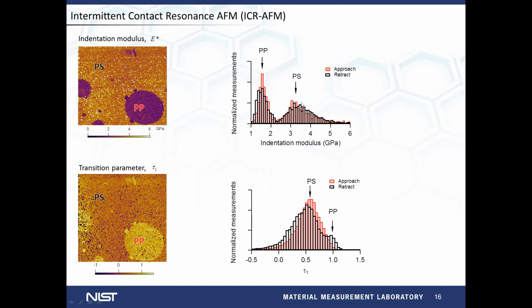Polystyrene was used as a reference material with the elastic modulus 3.4 gigapascal. Polypropylene was 1.5 gigapascal. But interestingly, there was also contrast in the transition parameter map. As we see the difference between these two materials, the value for the polypropylene was around 1, and this shows a larger contribution from the short-range adhesive forces. And this contrast is better observed during retract than approach, this being enhanced by the difference in contact adhesion hysteresis of the materials.